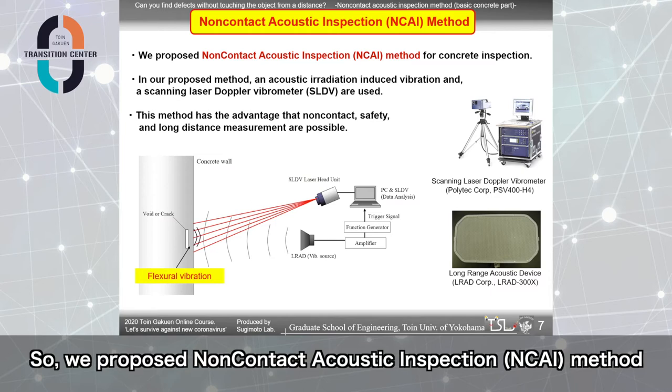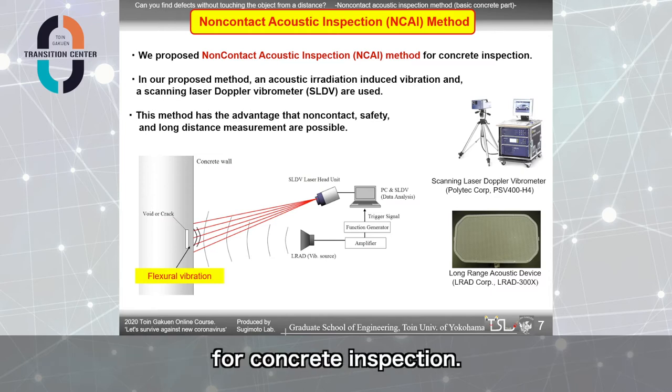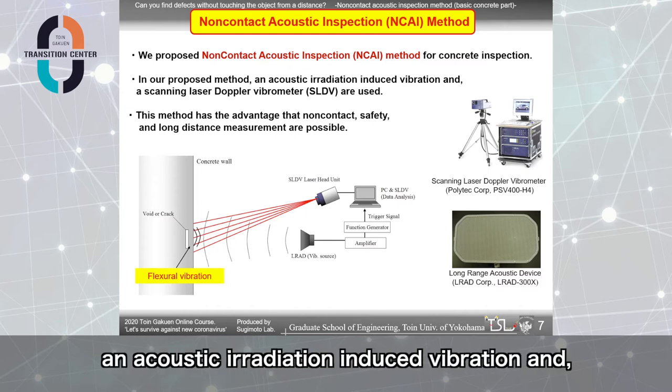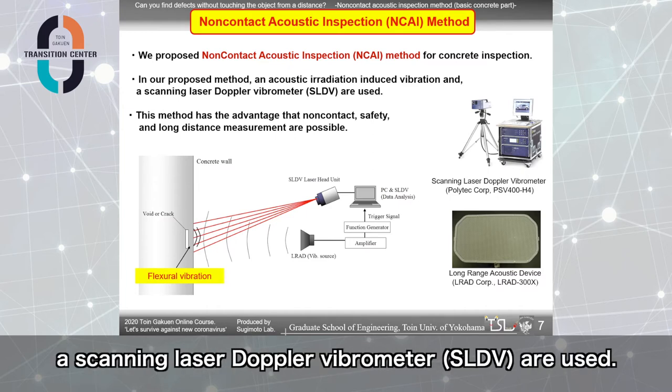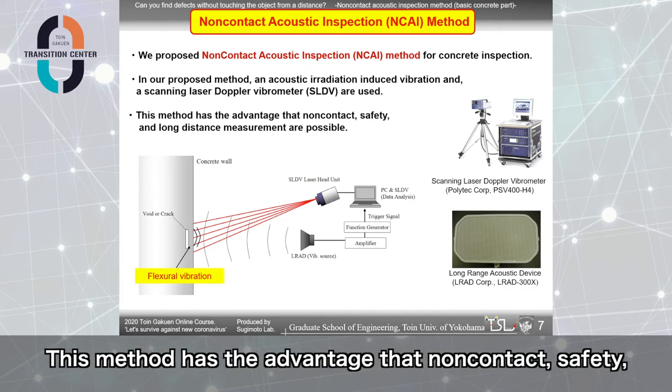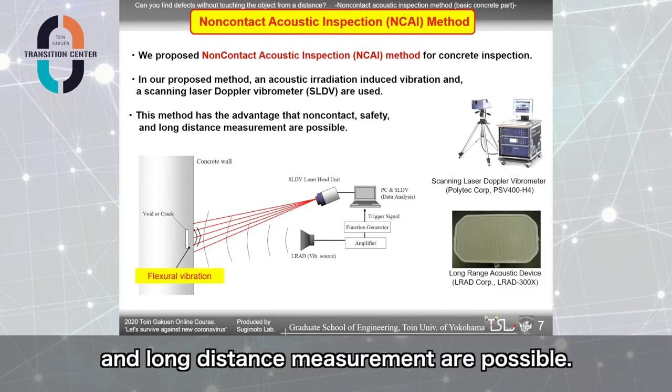So, we propose non-contact acoustic inspection, NCAI method for concrete inspection. In our proposed method, an acoustic irradiation induced vibration and a scanning laser Doppler vibrometer, SLDV, are used. This method has the advantage that non-contact, safety, and long distance measurement are possible.